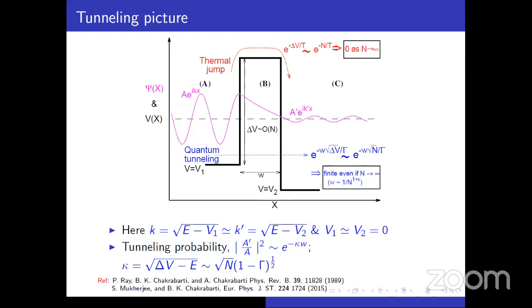So this is the probability, and the barrier is proportional to N. Since the barrier height is proportional to N, the probability is e to the minus N by temperature. So the escape time is proportional to e to the plus N. Whereas in a quantum case, there is another parameter which can be of great advantage: the width of the barrier, which doesn't come into the classical picture. A minimal estimate is like this. Suppose a plane wave comes in with amplitude A on the left-hand side, and after tunneling through the barrier the amplitude is A dash. I want to find A dash by A, and the square of that will give me the tunneling or escape probability.